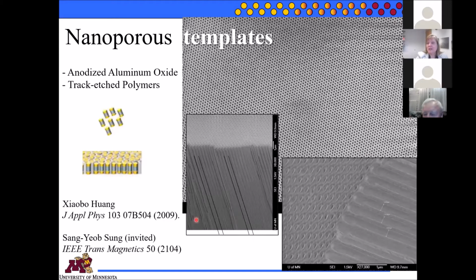Now, we also use track etched polycarbonate, and we have both freed the nanowires to use them. And I should say, we're using nanowires, but we can grow these segments pretty short, as you saw in the previous section. So they don't necessarily need to be long and thin for all applications.